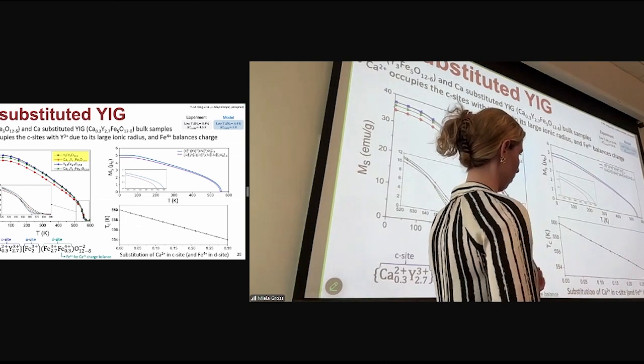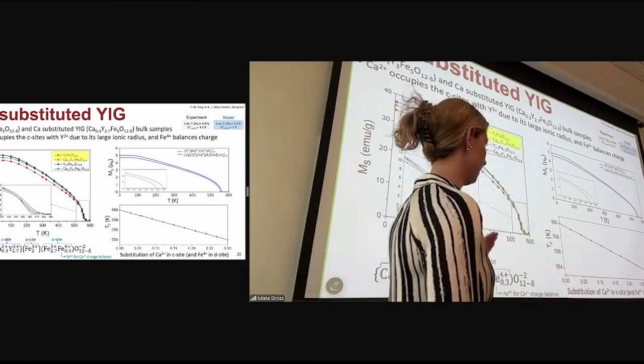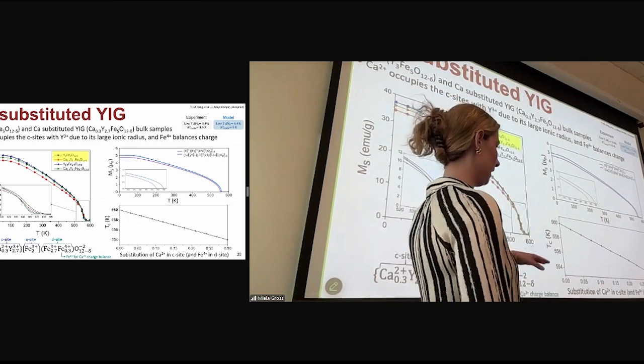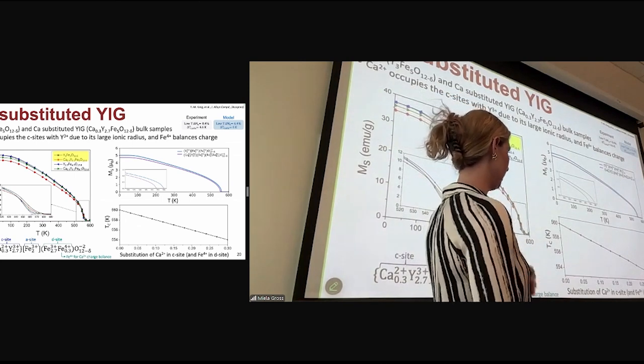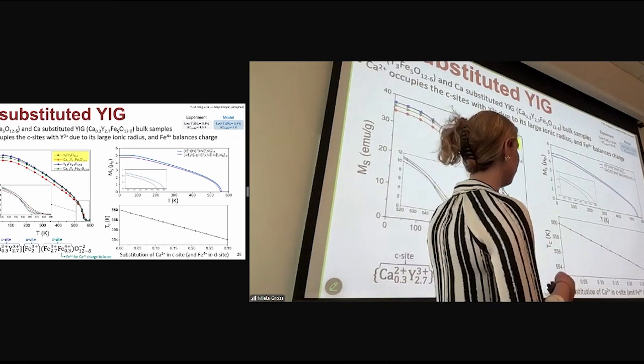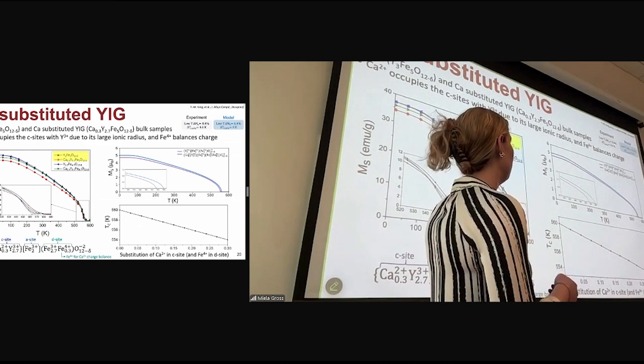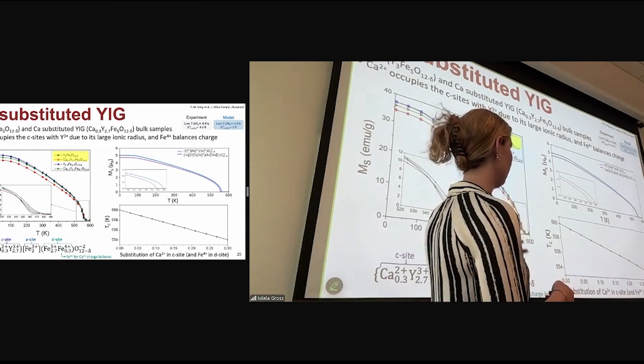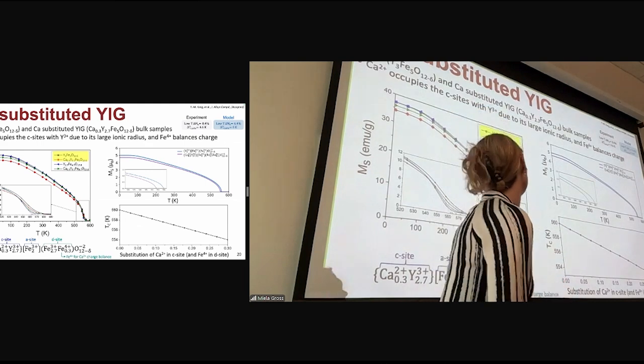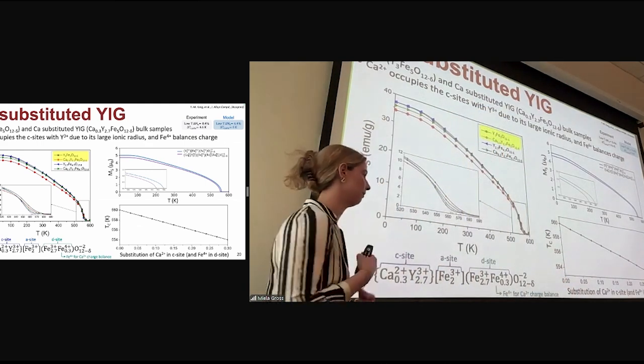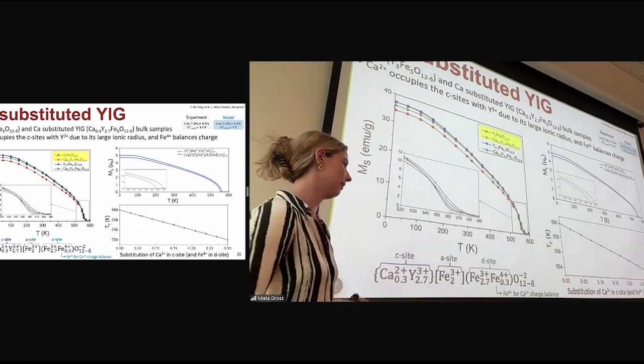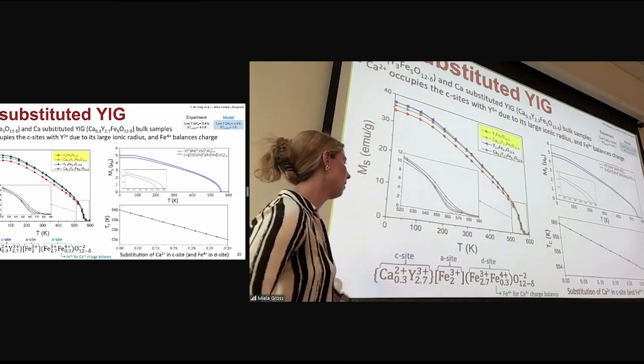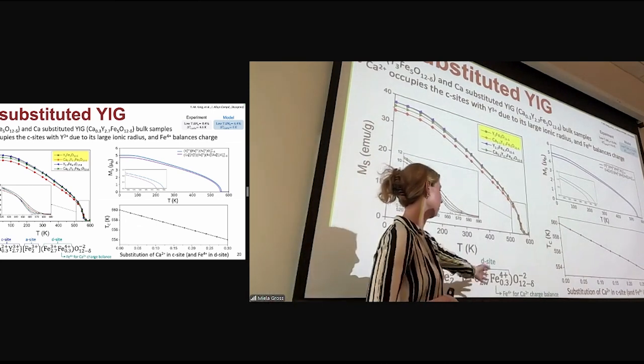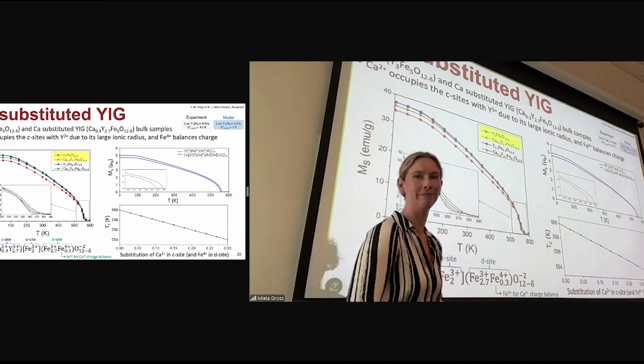We modeled that a little more closely, looking at increasing substitution of calcium in the C sites and iron 4+ in the D sites, and saw that lo and behold, the change in Curie temperature from experimental data matches what the model says, and same with the low temperature change in MS. So that was great because it also confirmed that not only do we have calcium 2+ in the C sites, but that introduces the presence of iron 4+ in these D sites.